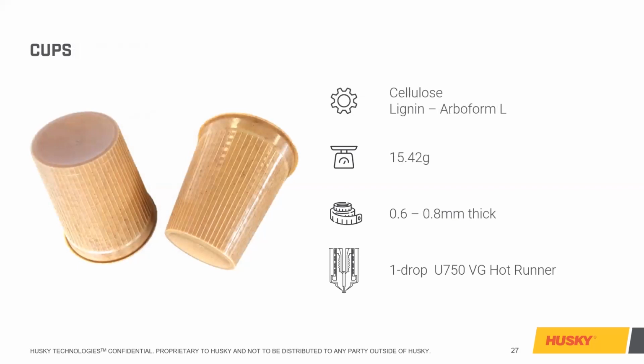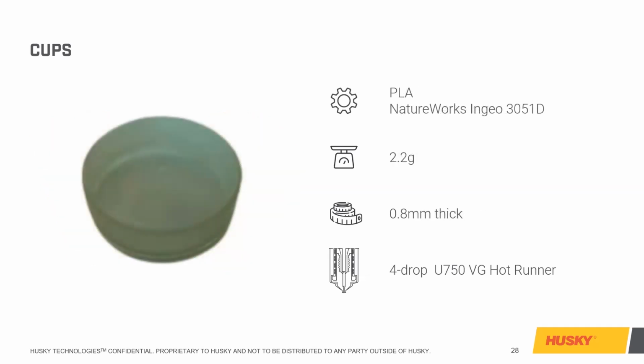This was an interesting one. This is a cellulose or wood pulp based resin, a fairly heavy part at 15.42 grams, wall thickness between 0.6 and 0.8, and this was a 1 drop system. The customer just did a prototype on this system. System ran pretty good with this specific resin. Another cup application with PLA, 2.2 gram, 0.8 millimeter thick, and this was a 4 cavity or 4 drop system.